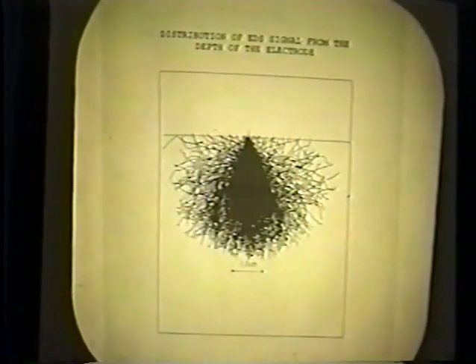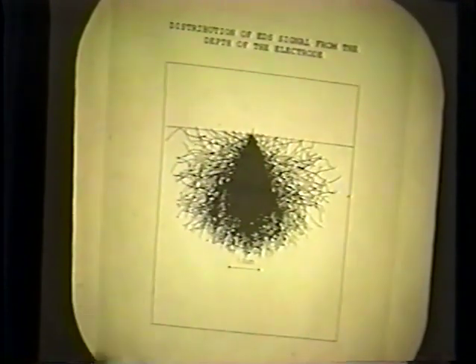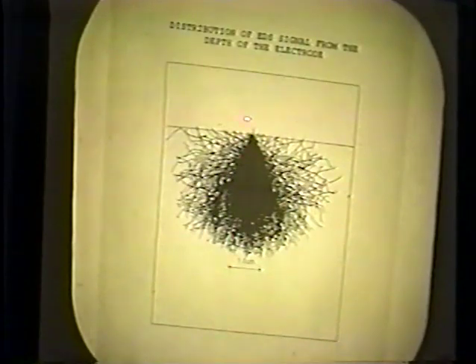While energy dispersion spectroscopy works differently. And this is the presentation of the energy dispersion spectroscopy signal. What we really get here is we irradiate the surface of the sample with a electron beam, which in our case is 25 kiloelectron volts, and that will produce knocking out of an electron from the inner core of the sample.